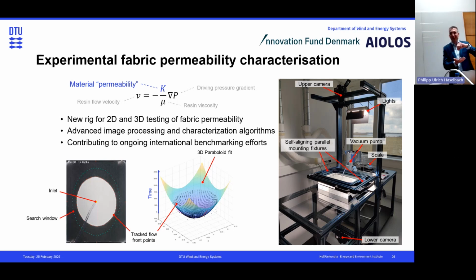So the resin is coming from the top and then spreading around, and then we do photo imaging. We look into how the resin is spreading in the material, and usually it's a kind of ellipse form, and then we track the flow front, and with that we can derive material permeability values that we later need for doing good simulations.